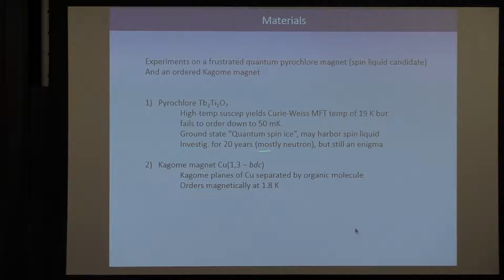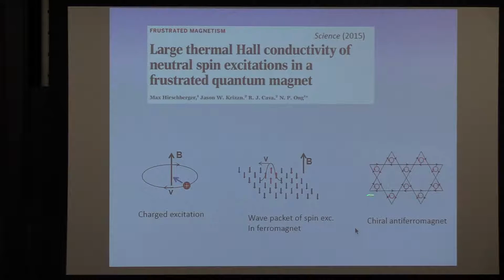Anyways, there's been 20 years of neutron experiments, and people get better and better neutron data, but it still remains an open problem. Absolutely no transport measurements on it. Well, a few transport, but not much. So we thought we would search for the effect in this material. This, by contrast, is an ordered magnet, but it has Kagome planes based on copper, and it orders at around 1.8 Kelvin. So okay, I don't need to say more about this.